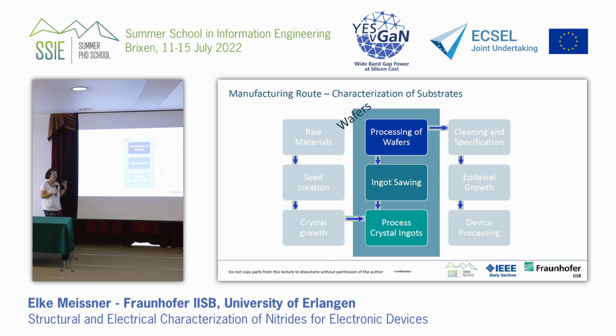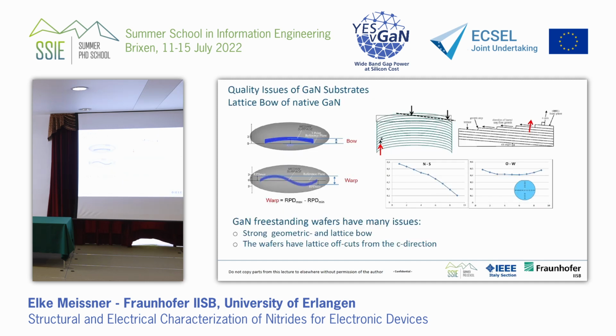This is awful if you consider it from a crystal growth point of view, but it works. So first of all, you have to trim it round, and you have to saw it in slices, which is also big mechanical action. There are wire saws. They come like these egg cutters with many saws, so it goes through it very fast because it must be efficient. And then you end up and see what was frozen, I would say, into the crystal. Then you have a wafer with some properties. And this is what goes into epitaxy.